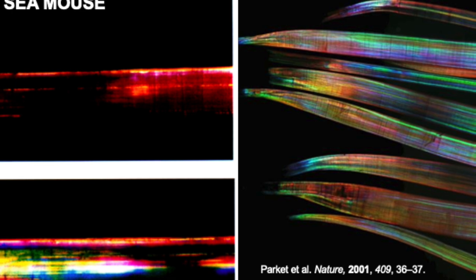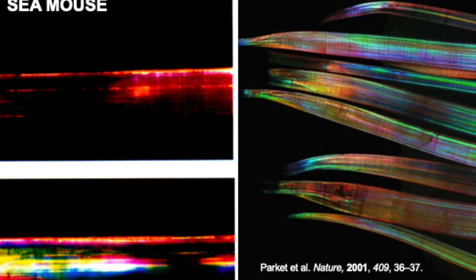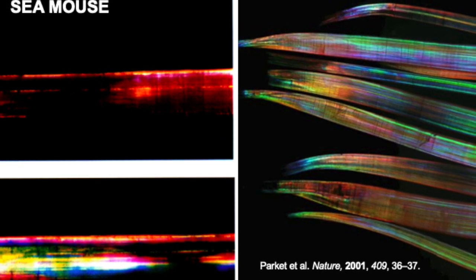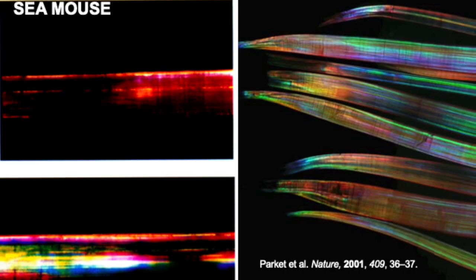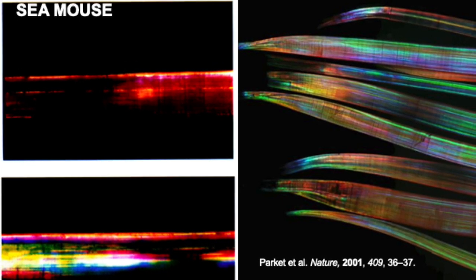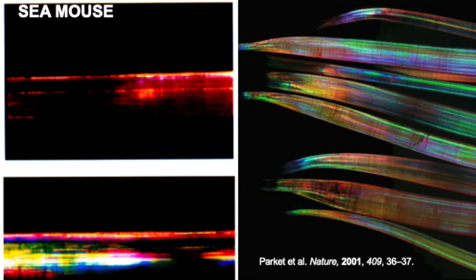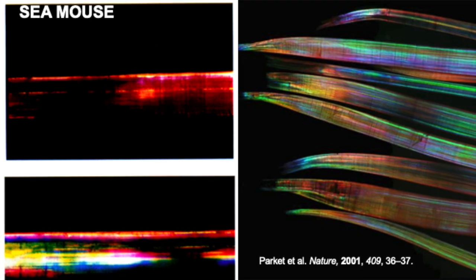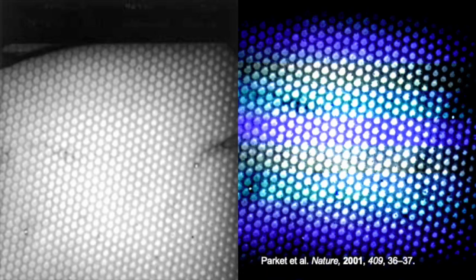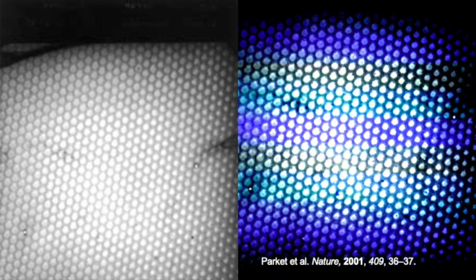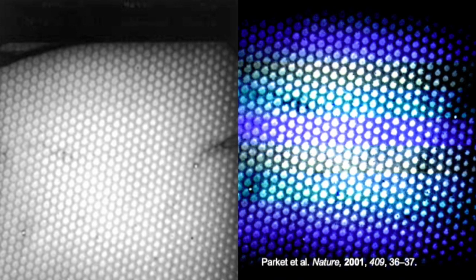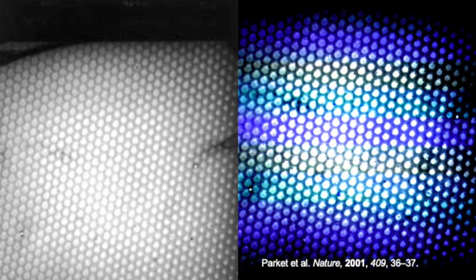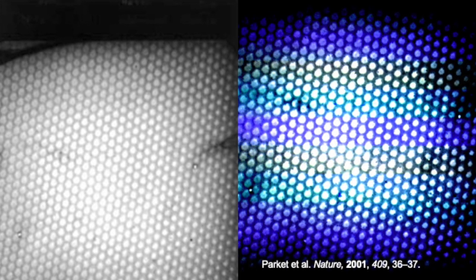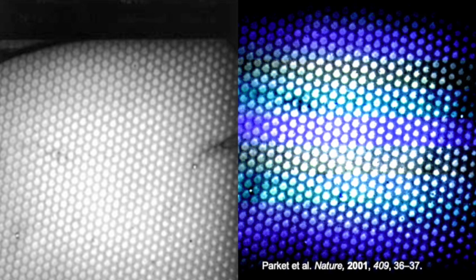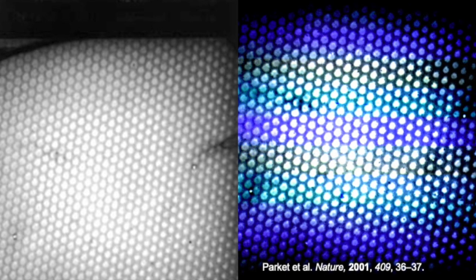Transmission electron microscopy (TEM) of a strongly reflecting red spine obtained by slicing the hair with a microtome into transverse sections reveals an array of hollow cylinders whose long axes run along the spine. The images correspond to the wall region of the spine, while the center remains hollow. The hollow cylinders have thicker walls near the edge of the spine to provide mechanical rigidity, after which the wall thickness decreases over a few layers to a constant value.